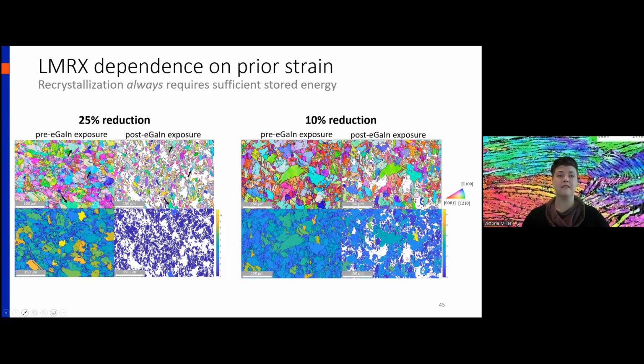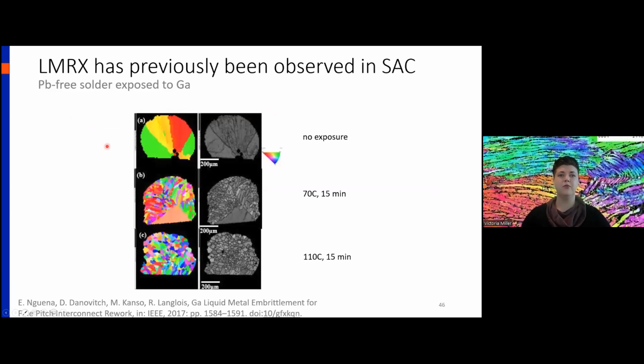I'll note that we are not the only people that have observed this. This was previously observed in SAC, a lead-free solder that was exposed to gallium. The initial grain structure of the solder ball started out very coarse. And then when exposed to gallium, you got recrystallization into this much finer structure, either partially recrystallized when exposed at 70 C for 15 minutes, or fully recrystallized when exposed at 110 C for 15 minutes.